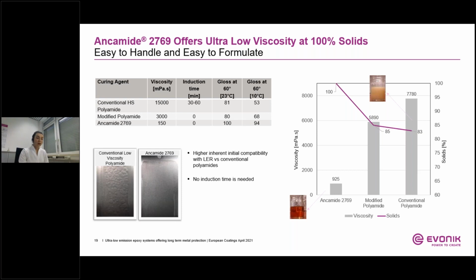Pictures on the left-hand side show wetting and film building of clear coat based on 2769 and commercial polyamides. On the right-hand side, we do see the mixture of liquid epoxy resin and Ancamide 2769, which provide a mixed viscosity lower than 1000 millipascal second and give a clear solution, which indicates a good compatibility. Versus conventional polyamide mixed with liquid epoxy resin gives a hazy solution, and the mixed viscosity is too high and requires a higher solvent content to be manageable.